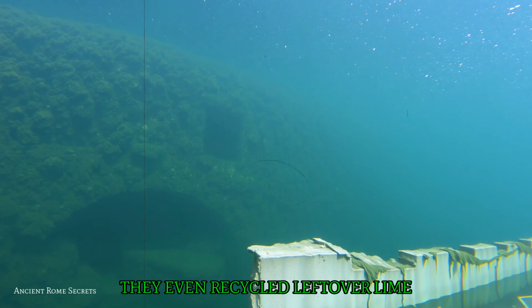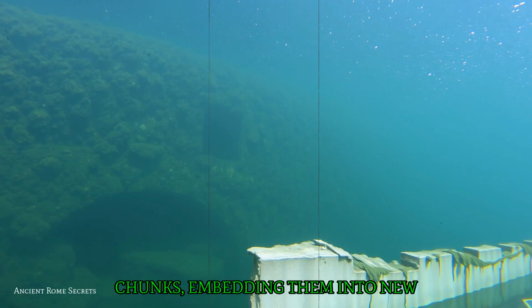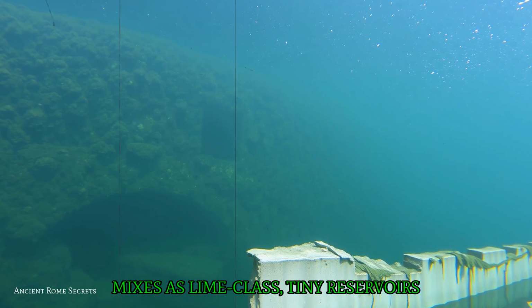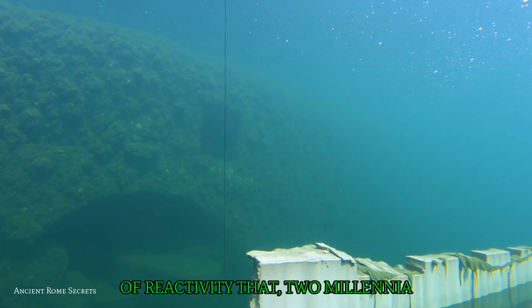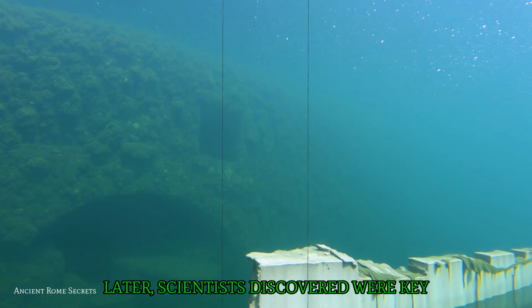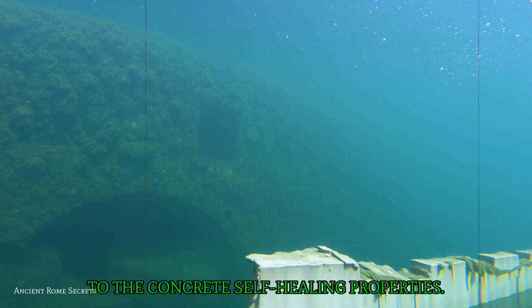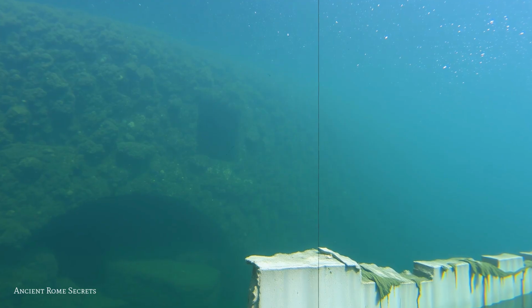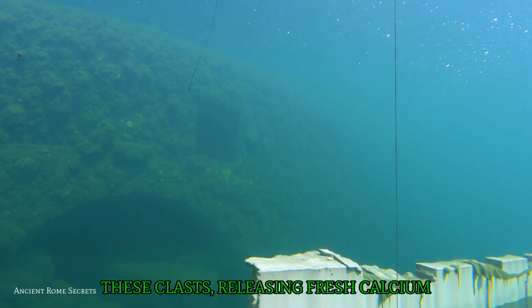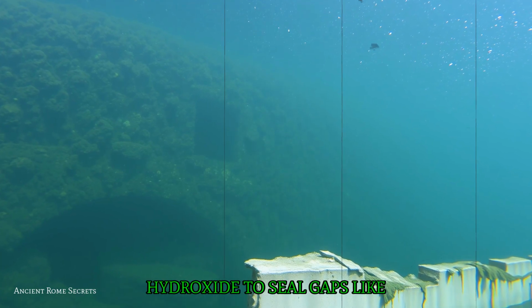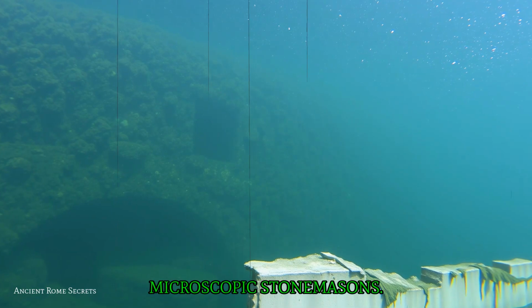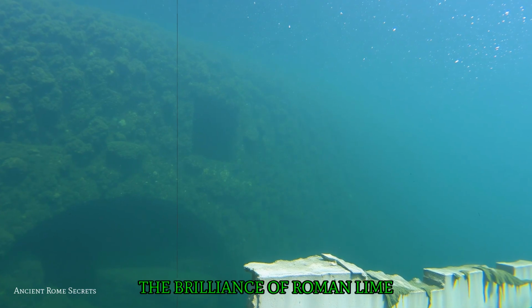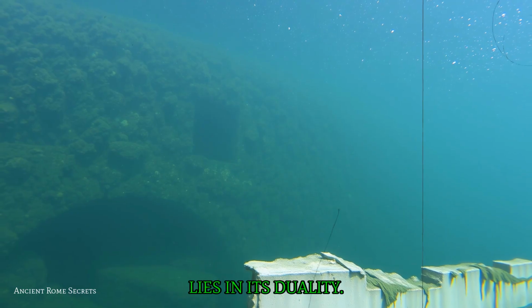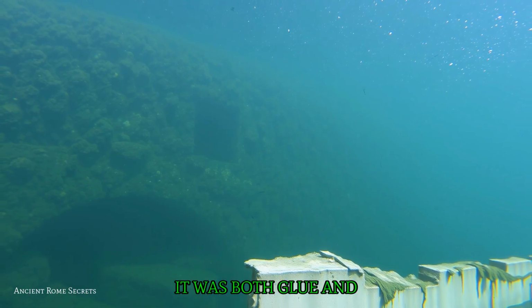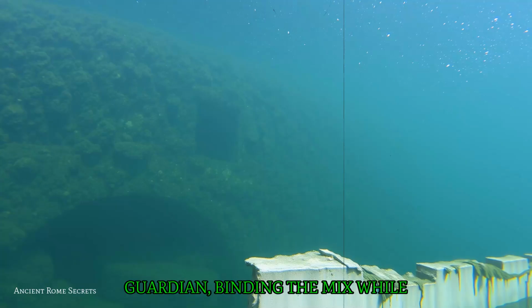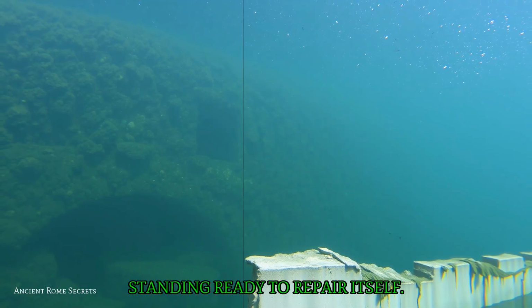They even recycled leftover lime chunks, embedding them into new mixes as lime clasts, tiny reservoirs of reactivity that 2 millennia later, scientists discovered were key to the concrete's self-healing properties. When cracks formed, water activated these clasts, releasing fresh calcium hydroxide to seal gaps like microscopic stonemasons. The brilliance of Roman lime lies in its duality. It was both glue and guardian, binding the mix while standing ready to repair itself.